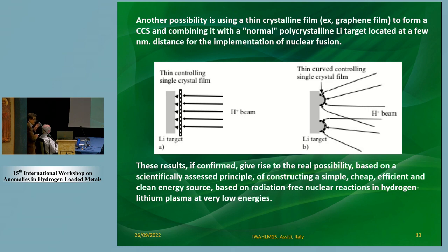The important thing is that the onset of this CCS is a single particle effect. So when the particle goes into such a state, it stays there. And then after, it can interact nuclearly with the lithium atoms, wherever they are. And there are other configurations also possible in this way. If confirmed, these results give rise to a real possibility, based on scientifically assessed principles, of constructing a simple, cheap, efficient, and clean energy source based on radiation-free nuclear reaction in hydrogen-lithium plasma at very low energy.